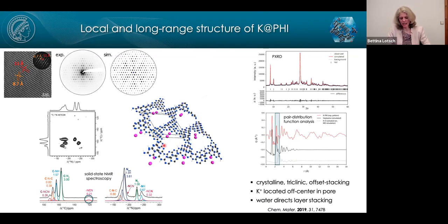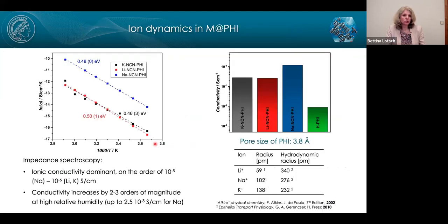What we can also say is that the potassium ions are, we believe, instrumental in determining the stacking structure of the system. You can see here it's pseudo-hexagonal, trigonal, when we just look at one single layer, but this is a triclinic system because we have this offset type layer stacking. Now, interestingly, the hydrated potassium ions are not only structure directing, but they are also mobile. So we made potassium PHI and also the homologous series, so other alkali metal PHIs. What we observe is predominantly ionic conductivity in these systems. So the hydrated ions are mobile with conductivities up to roughly 10 to the minus 6, 10 to the minus 5 Siemens per centimeter, depending a lot on the hydration state of these hydrated alkali metals.